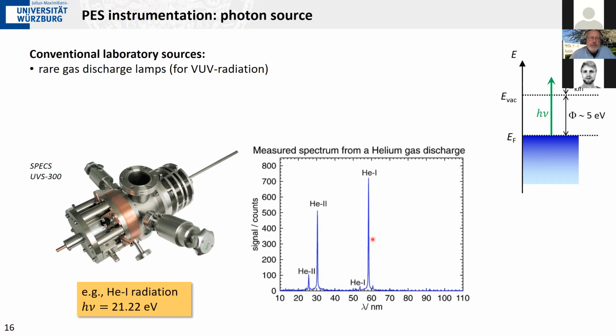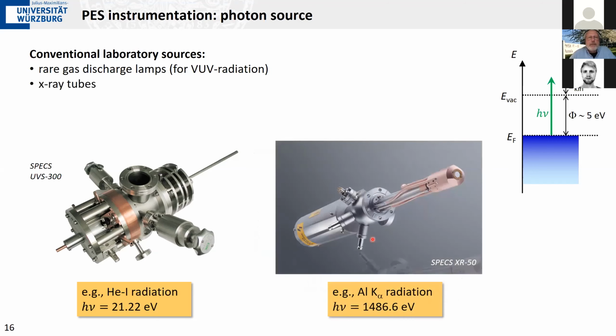The energy here is not high enough to excite core levels typically, and so you have to go to a source that produces X-rays, and that you do with a conventional X-ray tube, except that you have to do this in vacuum, because as we will see later, everything has to be done in vacuum here, but that's not a principal difficulty. And one excitation line that is used here very frequently is aluminum K alpha radiation. So you use aluminum as an X-ray anode, and the photon energy here is 1486 electron volts.